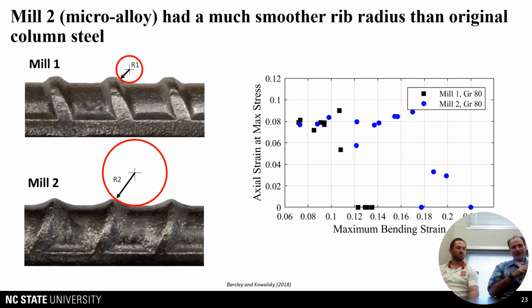And to complicate things, I remember we were looking at this, and you looked at the ribs for these two mills. So these were both microalloy, but the second mill had these deformations which were much smoother, right? I mean, you can see it there. The radius was much softer. And the hypothesis was, will these behave the same? Because if you look at this, the second mill seems like it might have a bit less strain concentration, whereas mill 1 has a sharper radius, maybe higher strain concentration. Might that lead to a lower bending strain?